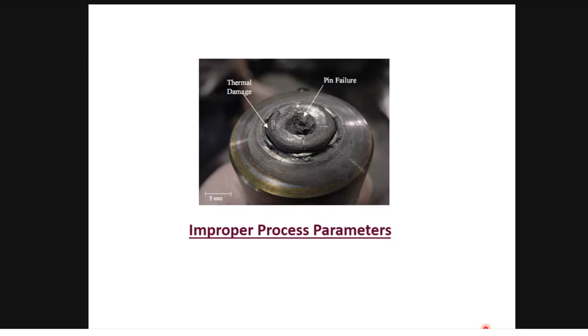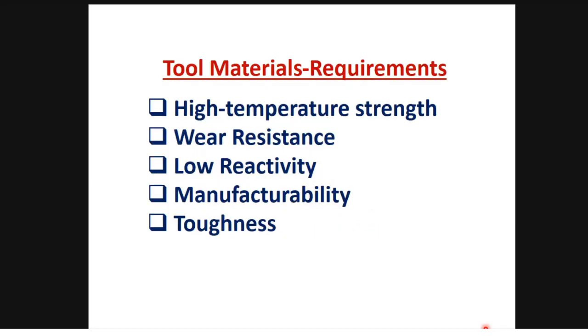With aluminum alloys and magnesium alloys, if you use improper process parameters, that will not affect the tool, but it will affect the joint, that is the base material. But when you're joining high melting temperature material, if you use improper process parameters, it will damage the tool. As I told you, the tool is the heart of the process, so the heart itself will be damaged. So one should be very careful while selecting the process parameters.